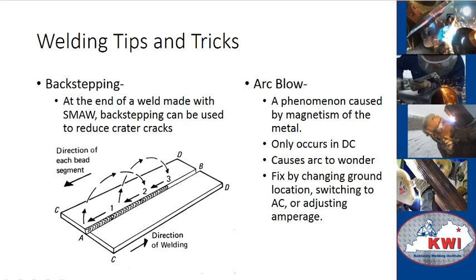All right, some tips and tricks. Backstepping. Occasionally we get crater cracks. So when we pull out of the end of the puddle too quick, we leave that crater dimpled. That dimple causes a depression. It causes stress risers, and that'll spider crack, a crater crack right there. So backstepping, if you can see the picture here, what's happening is I started here at the number 1, and I welded out. And then I skip back here to the number 2 and welded to my number 1. Then I skip back to the 3 and welded to my number 2. So my last weld, I'm going to start here at B, and I'm going to weld to 3. And what I've done is every time I ride my new weld up on top of my old one, I'm filling that crater up. All right.